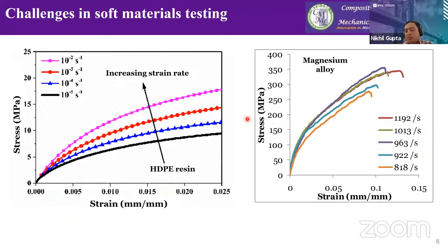So we won't go into those kinds of details just yet, but we want to look into these characterization complexities for these materials, because they make it more and more difficult for us to characterize the material properties over all the parameters which are required. So here you can see there is this HDPE resin, high density polyethylene resin, very widely used. It's around you in numerous products. And we are testing this material at extremely slow strain rates like 10 to the power minus 5. And here the highest one is 10 to the power minus 2. So all these are quasi-static strain rates allowed by ASTM standards.